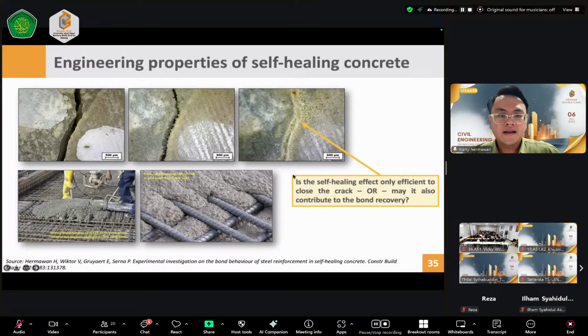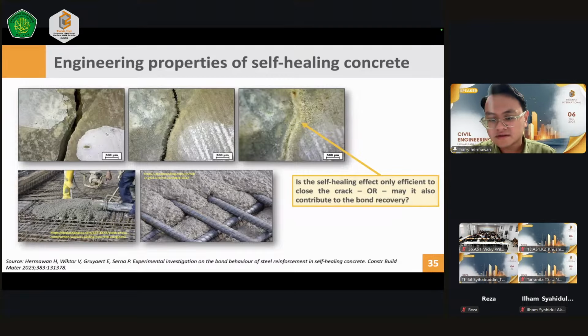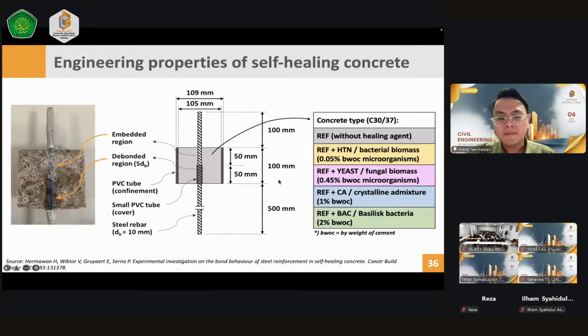Okay, so let's have a look. In order to assess the bond strength between the concrete and the steel reinforcement, we can study it by making a bond pull-out specimen. This is a special design to make a pull-out specimen. Basically, we use a steel reinforcement with a rebar diameter of 10 millimeter, and we also use a small PVC tube inside, and we make 5 types of concrete mixture. So what are the 5 types?